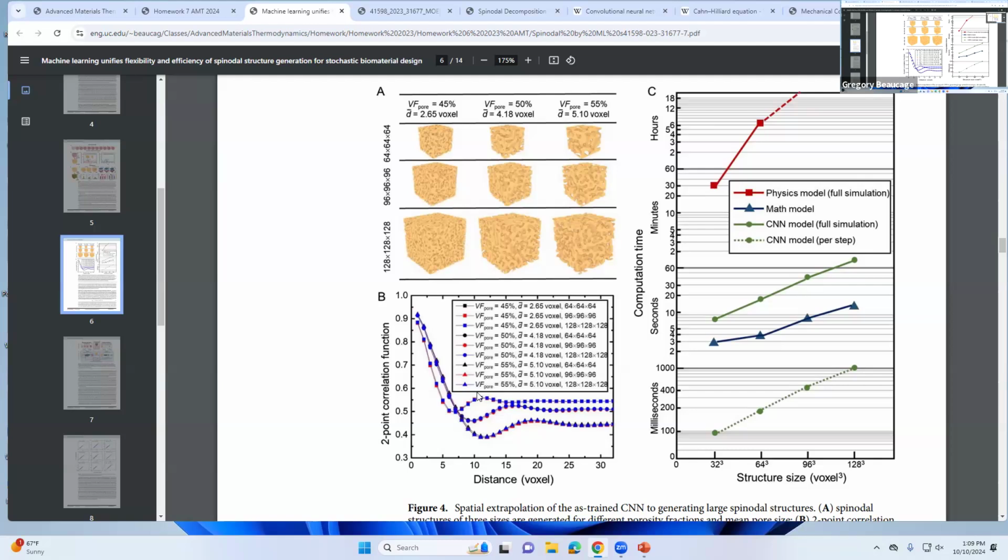So if you have high density for the first one, then you'd expect to have the phases closer together. That's how it gets high density, because the hole between them is smaller. So that agrees, like as you decrease the density, the struts get separated by a bigger distance. That's because the peak moves to the right in this distance axis.